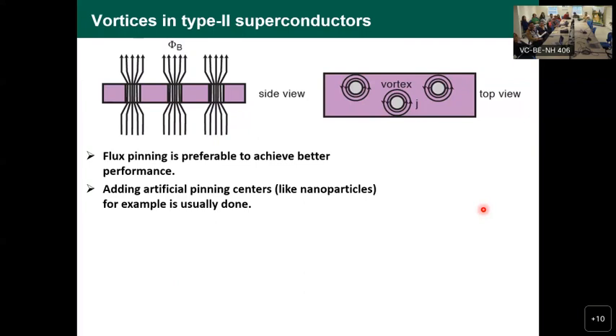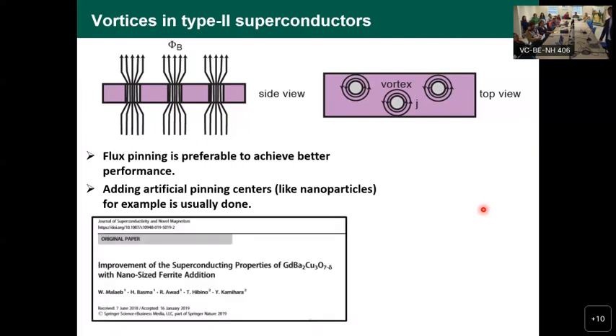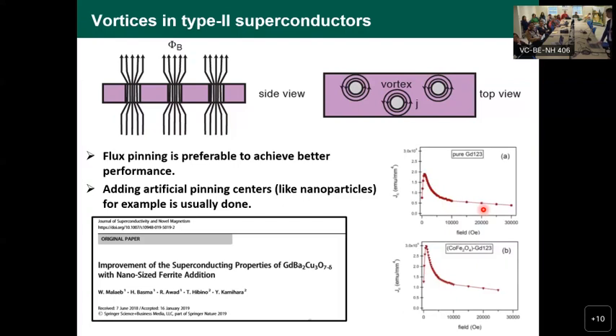Usually people look for what we call artificial pinning centers. One way is to add nanoparticles, because they do not interfere with the structure itself. They do not change the structure, but they act as artificial pinning centers. Why are we confident about this point? Because we tried it for the copper oxides, the previously discussed high Tc family. In this compound, also in collaboration with Kamihara, it showed positive results. We could really achieve improvement in the superconducting properties. That's why we will do similar work for iron pnictides.